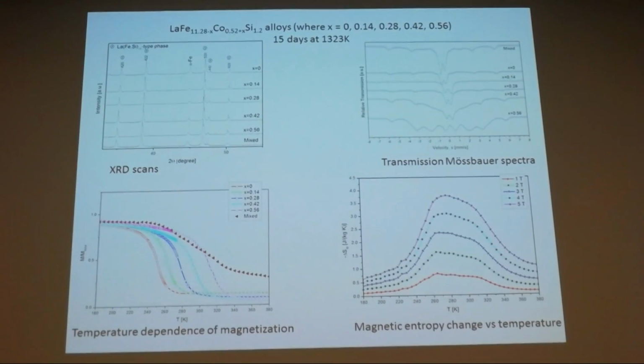One example of our work is the lanthanum iron cobalt silicon alloys with various cobalt contents, which show that with the increase of cobalt content, a change of the unit cell parameter for this lanthanum iron silicon 13 phase occurs, and also magnetic properties, shown by the Mössbauer spectra analysis and by the magnetization versus temperature measurements, show such a change. We have made a mixture of all those compositions by crushing to powder, ball milling, and compacting